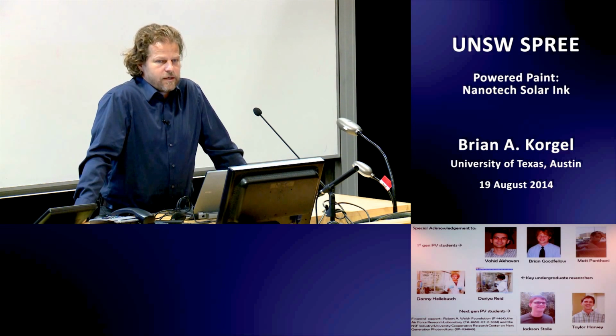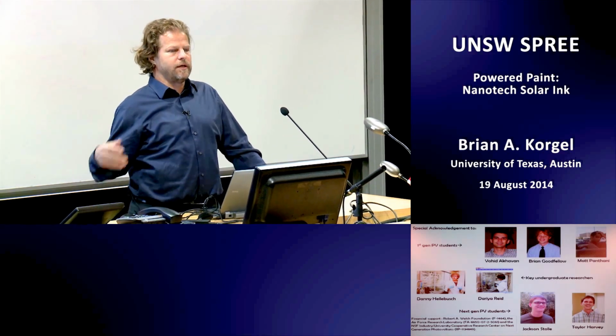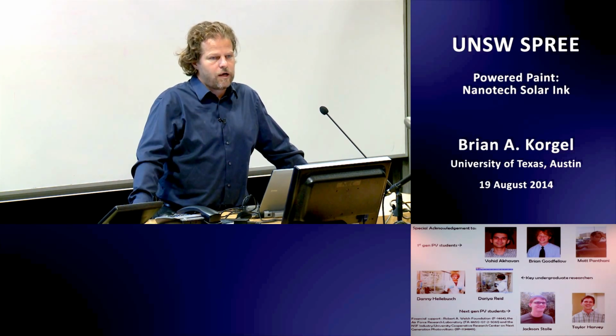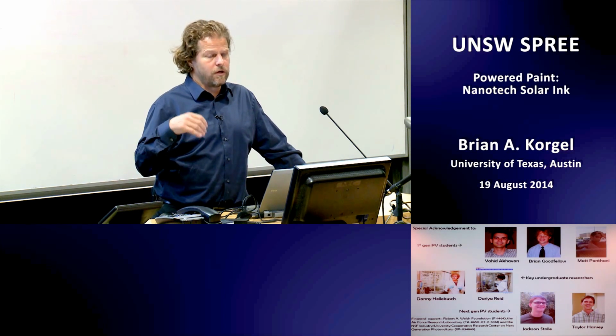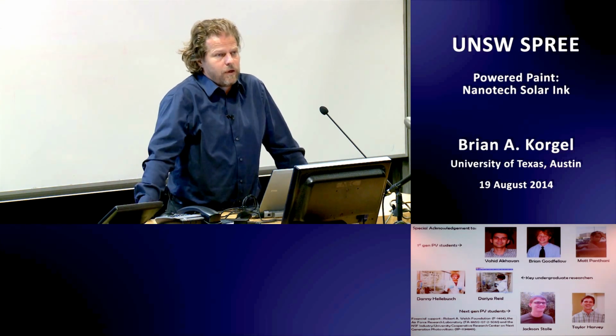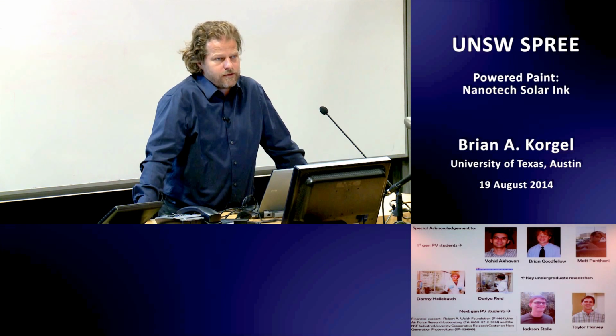So in the selenization process, sodium is really critical. To get up to 7 or 8% efficiency in the selenization process of CIGS, sodium is really crucial for the sintering. In our case, these as printed devices are not sintered at all. Where we're looking at the possible role of sodium, where it could be really important, is in the photonic curing. So there, we're dosing films with sodium to see if that influences the sintering under the photonic curing process at all. And that's kind of unexplored territory, just because you're really in this kinetically limited regime, and you don't have long-range diffusion of elements the way you do in selenization. But there we're really looking at sodium and the role of it.